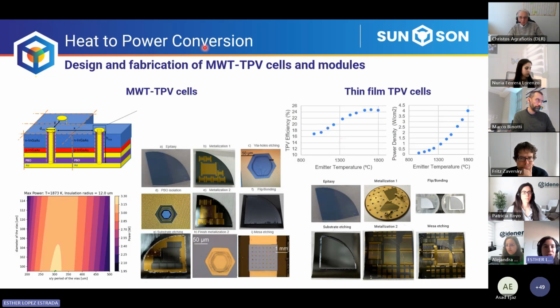Regarding the heat to power conversion part, we have used 2 kinds of TPV cells, what are called thin film TPV cells that include a back reflector in the rear side of the cell to boost the efficiency up to 25%. And also what are called metal wrap-through TPV cells, where the front contact of the devices can be transferred to the rear side in order to increase the active area at module level, because this way we can remove some specific parts that are dedicated to interconnection of the devices.